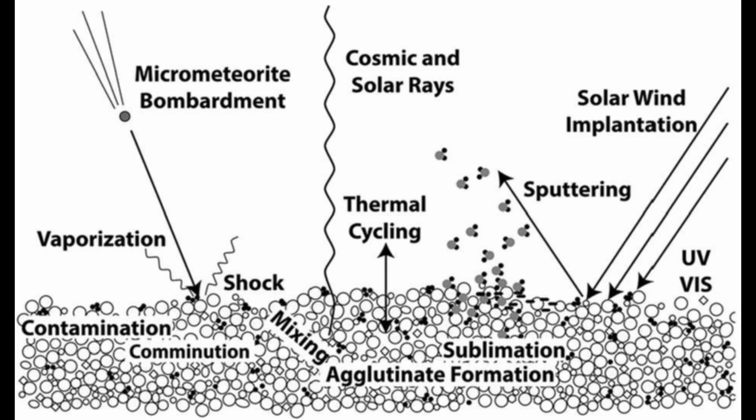So why do the lunar and Mars regoliths have such low seismic velocity? We found that velocity increased with increasing grain size of the sample, which is in contrast to most of the literature saying that grain size shouldn't affect the velocity of a sediment. So maybe this only holds true for sediments we find on Earth with larger grain sizes, but that relationship breaks down as we get smaller and smaller in environments we only see off-planet. The best explanation for the small grain size is that other planetary bodies have different weathering processes — for example, micrometeorites impacting the surface of the Moon or an asteroid break those particles into even smaller pieces. Our data wasn't sufficient to prove any of this since it was an accidental finding, but it's an exciting area for future research.